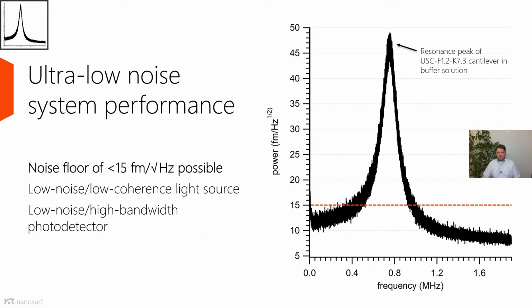So one thing that we took care of is that the system has a low noise floor, so it has a low noise performance. This is important because if you have a high noise in your system, you're not able to detect small changes and do gentle imaging. So particularly, we can reach a noise floor of the system which is well below 15 femtometer per square root hertz, which is excellent. And we get there by using a low noise and low coherence light source, but also low noise in the high bandwidth detection. So also at high frequencies we still get low noise values.